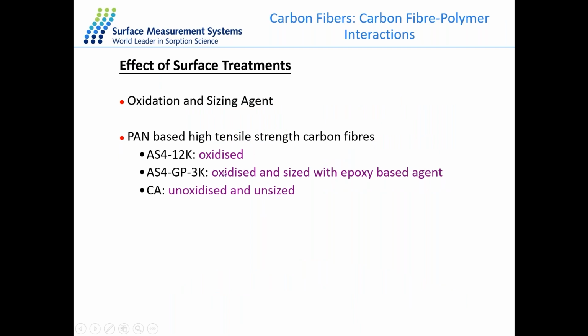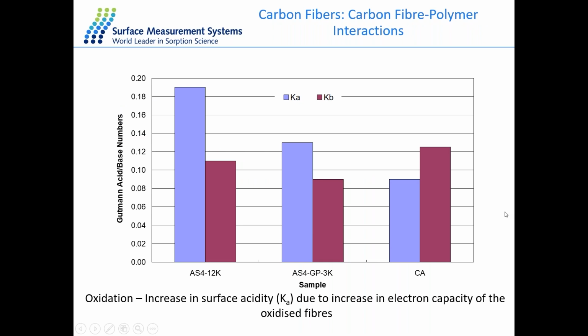We've then carried out the experiment and oxidized our sample. So this is our AS4 oxidized sample. We've also taken our AS4 sample and oxidized it with epoxy agents. And we've also used a control, unoxidized and unsized material. From this, we want to understand how oxidation and sizing affect our samples. For this, we've calculated the Ka and Kb of our samples, the acid-base contribution. What we can see here is that, of course, during oxidation we have a much higher Ka to Kb of our material, especially compared to our control.